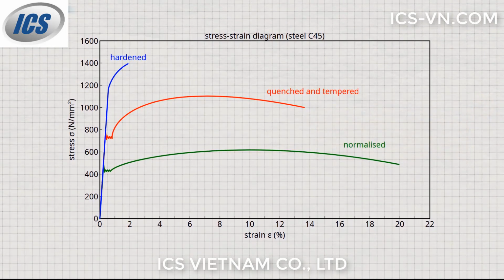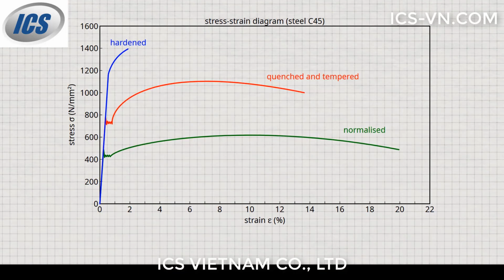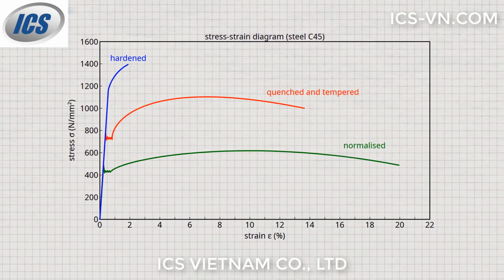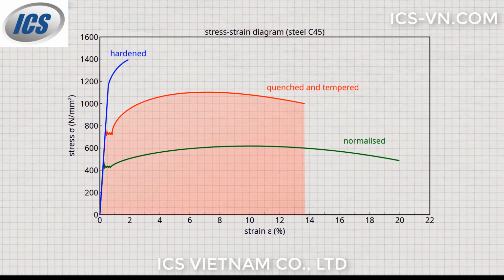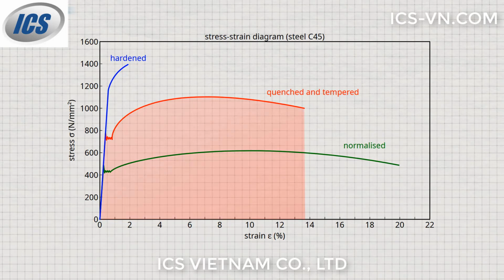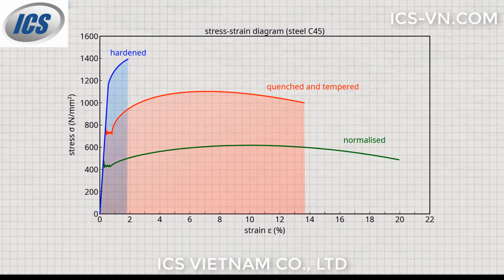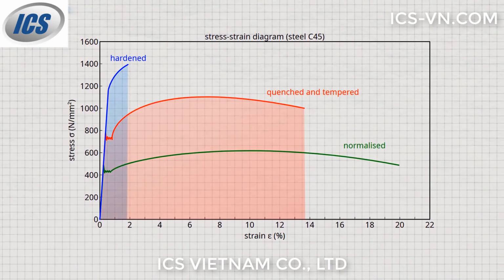Because of this combination of high strength and high toughness, quenched and tempered steels can absorb a large amount of deformation energy before fracture. This is shown by the area under the curve in the stress-strain diagram, which is a measure of the energy absorption capacity of the steel. While the hardened steel can absorb very little energy, the quenched and tempered steel has a much higher energy absorption capacity.